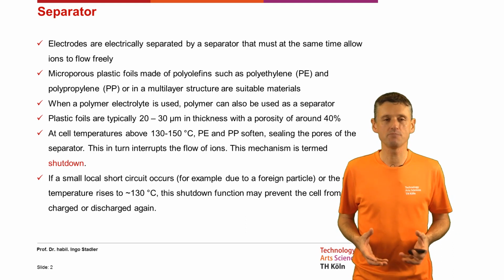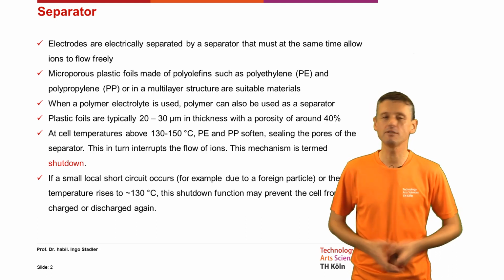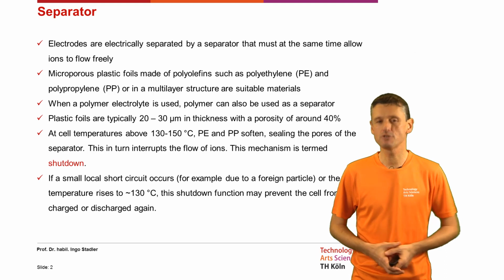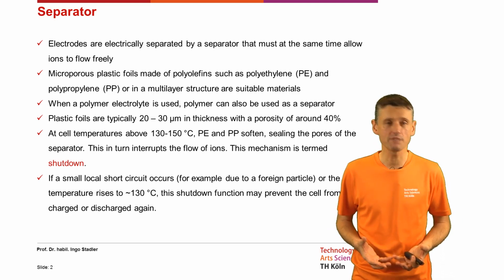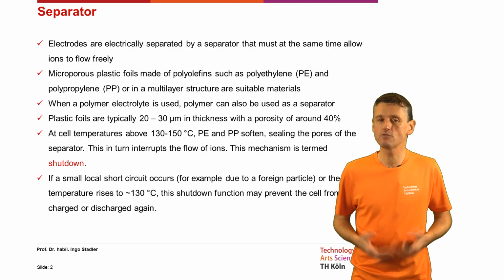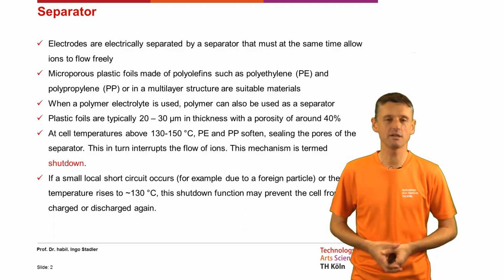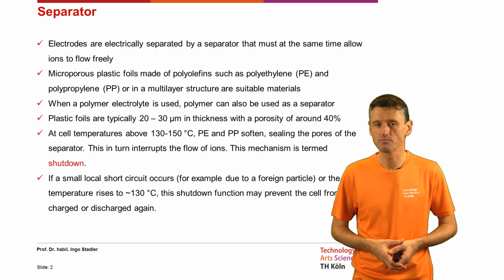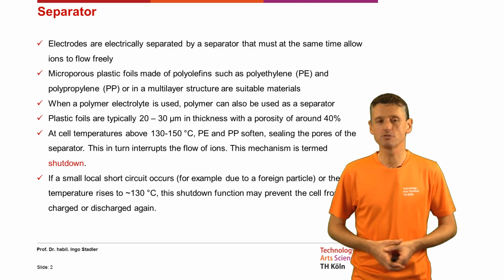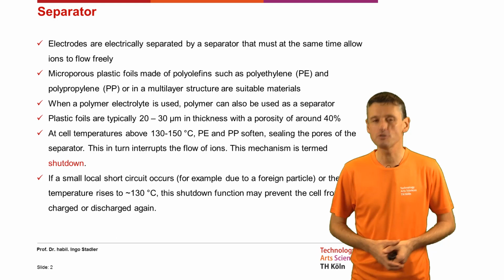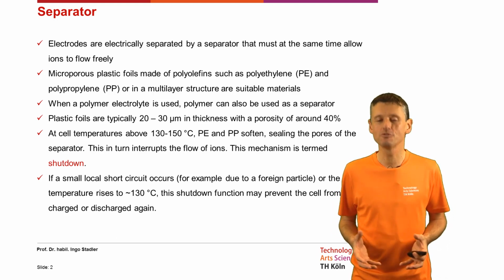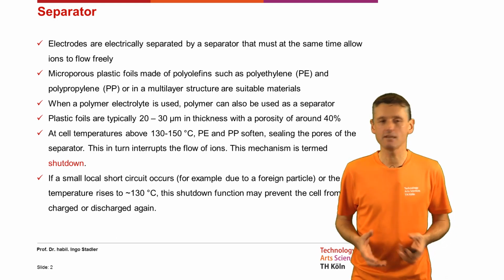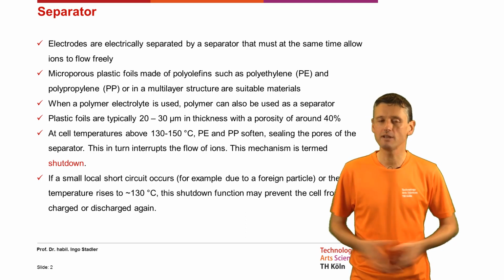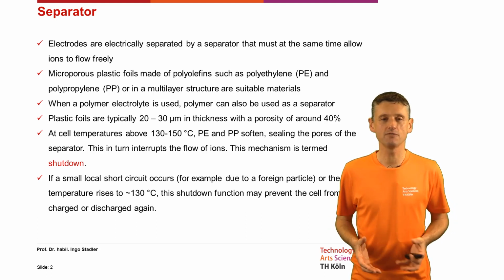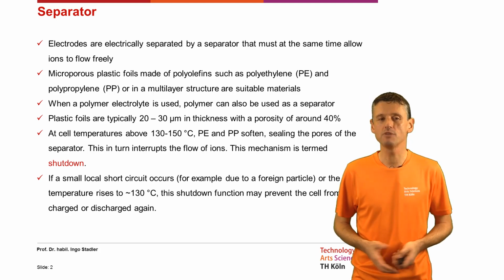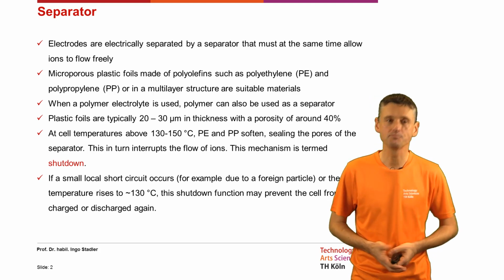At cell temperatures above 130 to 150 degrees, PE and PP soften, sealing the pores of the separator. This in turn interrupts the flow of ions. This mechanism is termed shutdown. If a small local short circuit occurs, for example due to a foreign particle, or the cell temperature rises to about 130 degrees, this shutdown function may prevent the cell from being charged or discharged again.